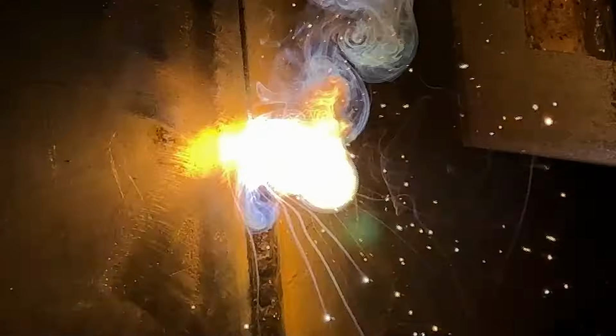So we kick things off with 65 amps using 2.5 6011 rods, but the heat was a little bit too much and the keyhole was blowing open and we were chewing those edges away. After noticing this, we had to adjust the settings to gain control of that weld pool and keep consistent penetration on the back of the joint. To do this, we dropped our amperage to 55, which brought us back in control, and the weld began running a lot smoother, and we've got much better control, which means we're pushing metal through the backside to get a